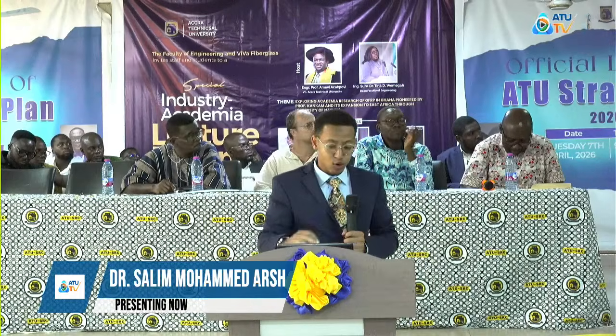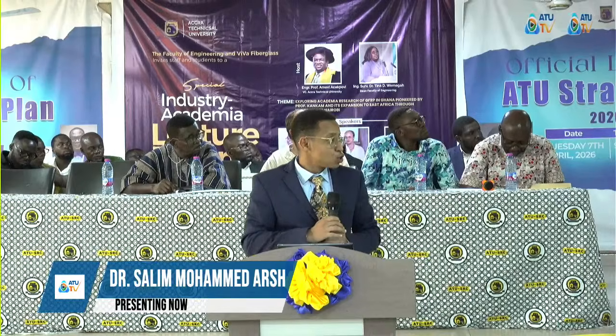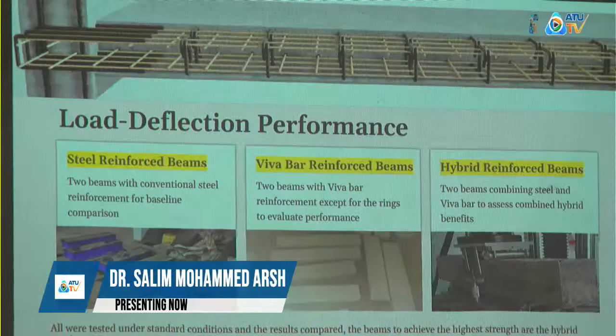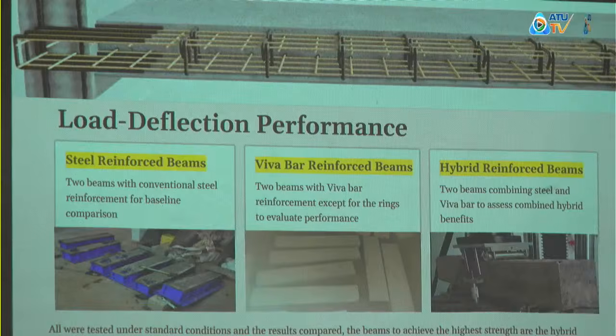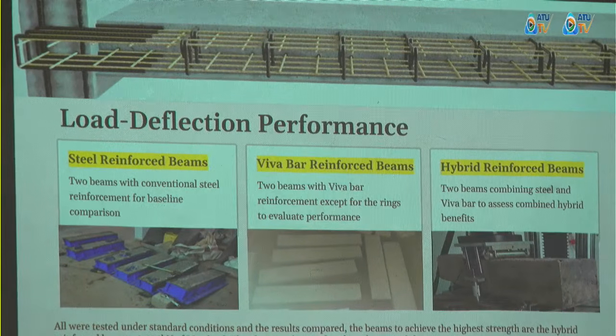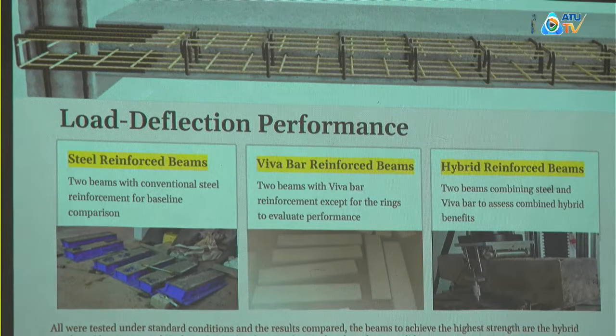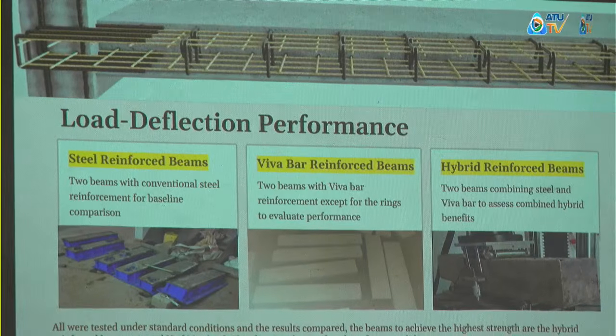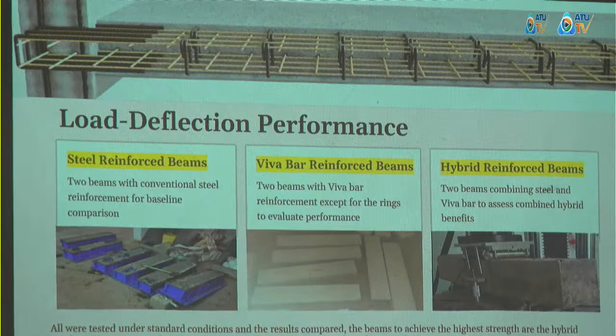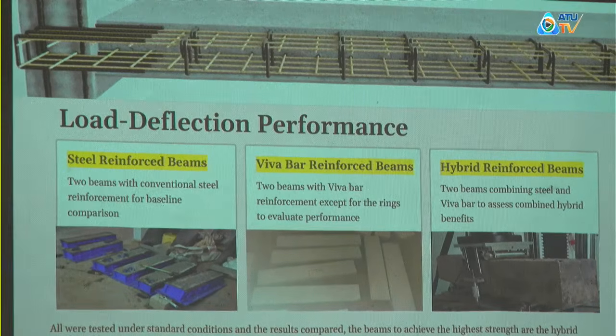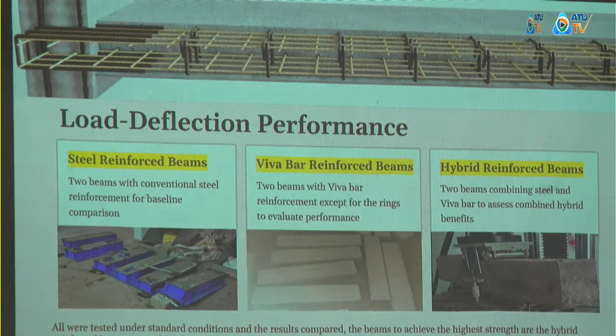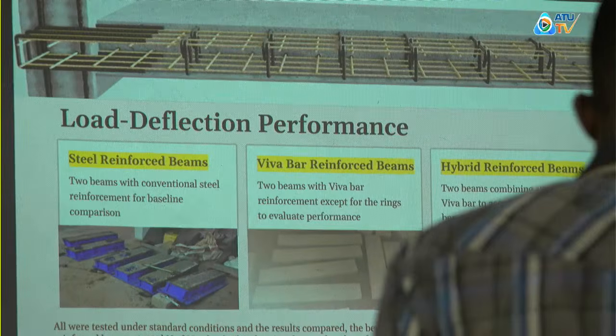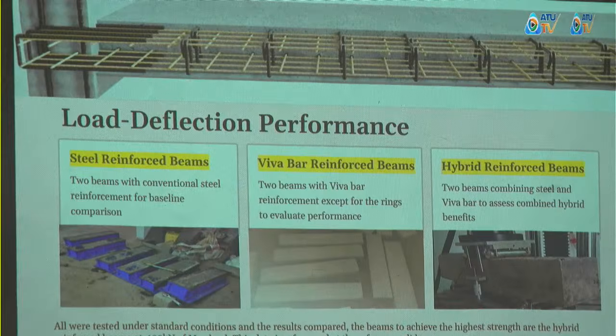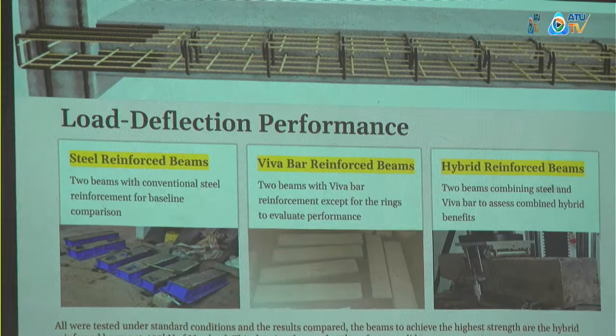Moving on to the next slide, which took me a really great time. This was the beam loading test, beam flexure. For this specifically, I casted 6 beams, whereby 2 of them were reinforced fully with steel. 2 other beams were reinforced with fiberglass, except for the links and U-shapes at the end. And the last 2 were reinforced with the hybrid approach that Viva is vouching for, whereby in the lower members where there is high tensile requirement, I use the Viva bar, and then the top members which are subjected to a bit of compression as well, I use the regular steel from the market. As you can see, I left the beams to cure for 28 days before taking them out and putting them in the flexure machine.